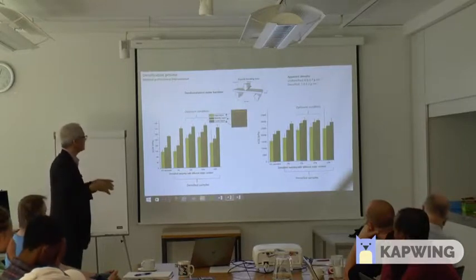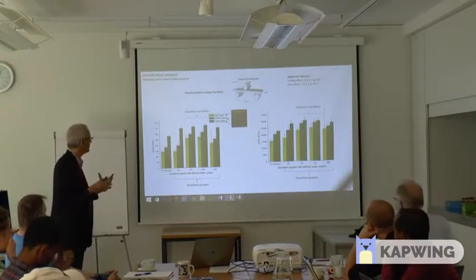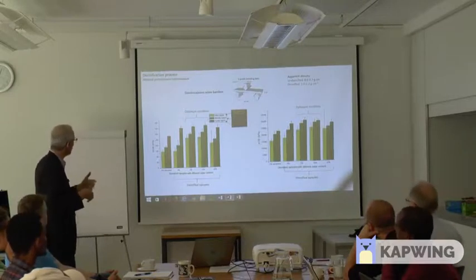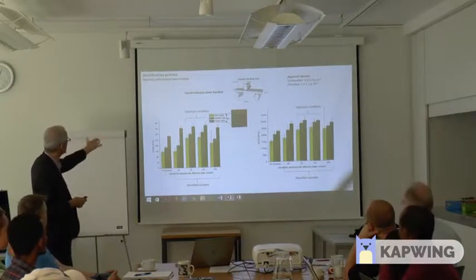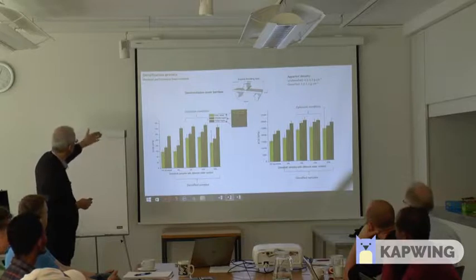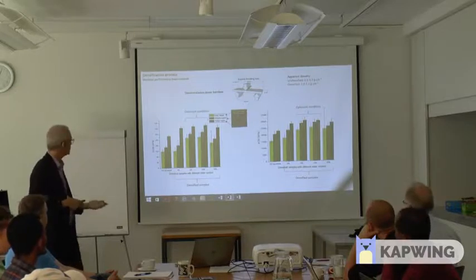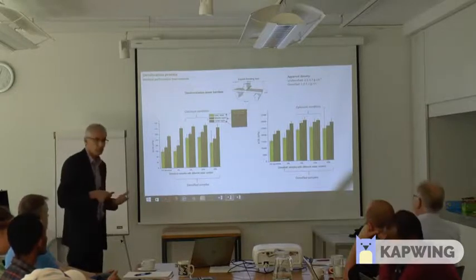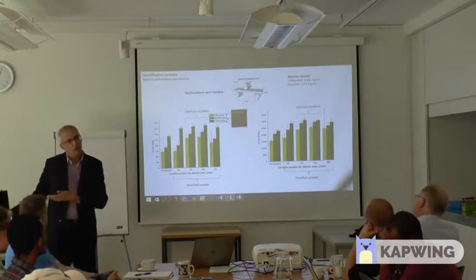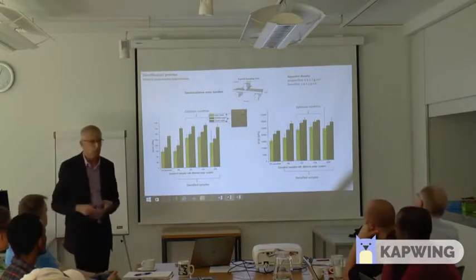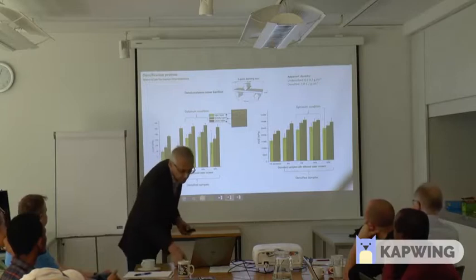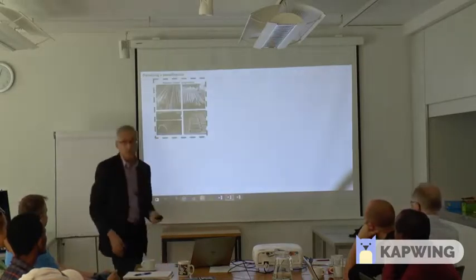So there is a great potential for this material, you see the performance is very nice. You can achieve up to 300 megapascals in modulus of rupture, which even for wood, I think is a good performance. So it's a material that can really be used for several different applications.